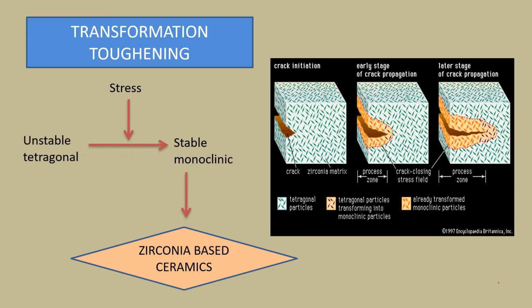Then the next method we have is transformation toughening. Here partially stabilized zirconia is dispersed into the glass phase of the porcelain. This partially stabilized zirconia is made by addition of yttria to the zirconia. This yttria added partially stabilized zirconia is usually in the tetragonal form. Under stress, this will get converted to the stable monoclinic form, which is 5% larger in volume, and this is called stress induced phase transformation. This monoclinic form, which is larger than the tetragonal form, will try to compress and prevent the crack propagation.